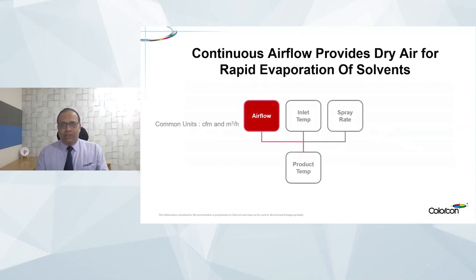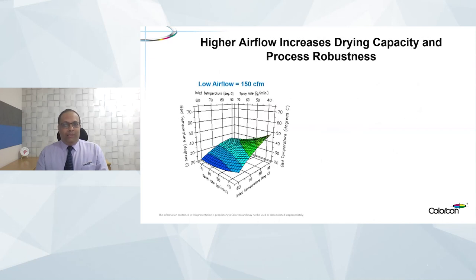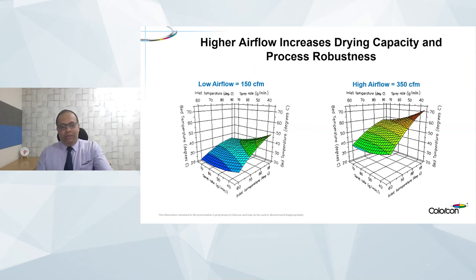Of course, airflow is often a factor which gets a little less attention compared to temperature and spray rate. The airflow is the overall volume of air that is coming in to dry. Imagine the blower or the air drying principle, where sometimes in a humid environment, it's just the quantity of air that is coming that can help dry the substrate. So how does it impact? Basically, it is important to measure this airflow. Of course, it is very important to make sure that we are operating the equipment used for coating at its maximum efficiency, at its highest possible airflow, and yet still achieve a good negative pressure.